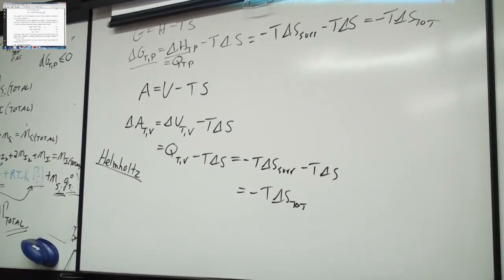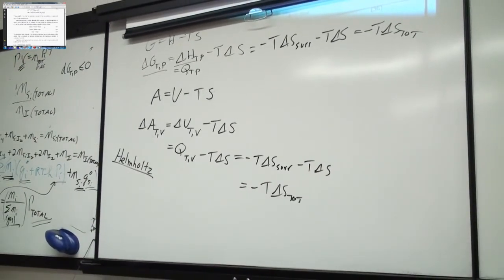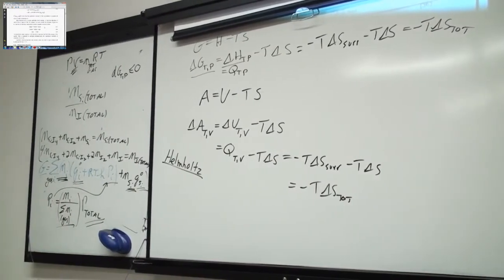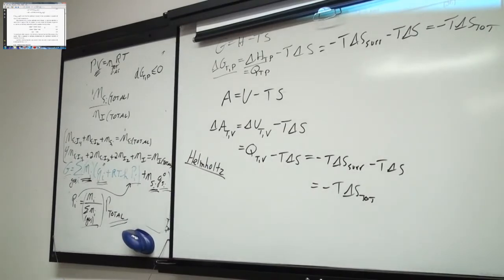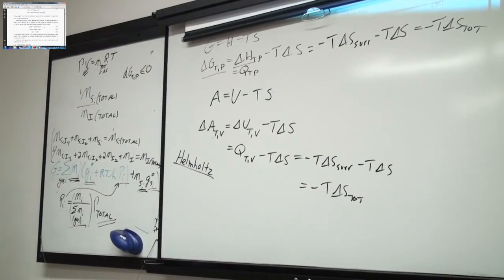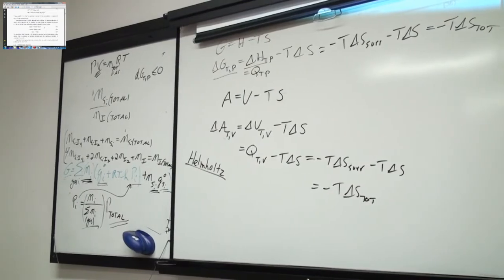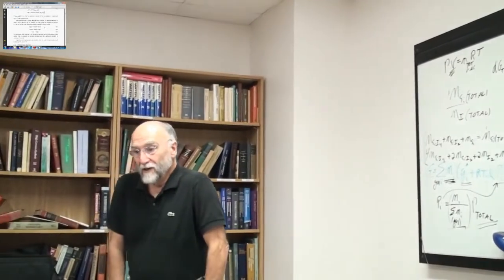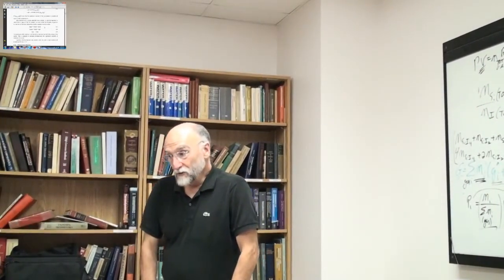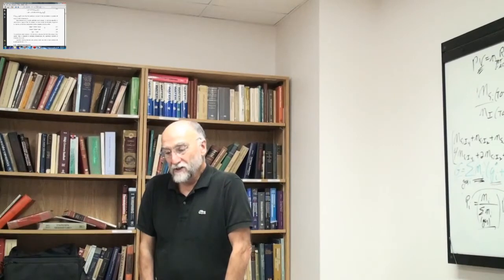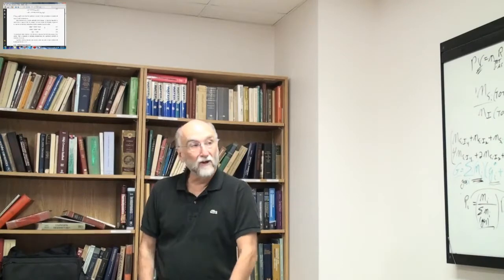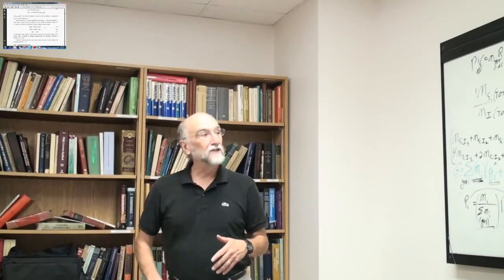We don't do this because we already have this nice expression, delta G is delta G naught plus RT log P, expressing the Gibbs energy in terms of pressure and everything. It's easier; otherwise you'd have to express everything in terms of volume. You'd have to rewrite your equilibrium constants, your delta G's at constant volume. Especially when you're getting into things like solutions, the sort of minimization that we do in FactSage, you would have to express everything in terms of temperature and volume, with constant volume heats of mixing and so on. It's just much more convenient to do things at constant pressure.